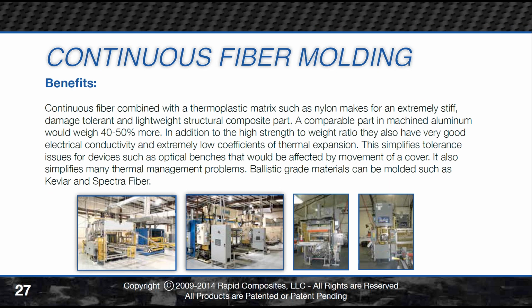So for instance, we have materials that can be consolidated at 1 millimeter, 2 millimeter, even quarter millimeter thicknesses in quarter millimeter increments. In fact, up to 6, 8 millimeters even in thickness, that can be heated to their melt point, so they become drapable like a wet towel, hot stamped and simultaneously cooled inside a matched metal tool in a vertical press.